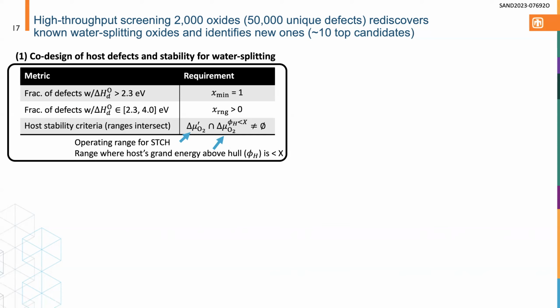And then we need at least one defect in the critical range. Nominally, you might want more than one defect in that range. And then the big thing that we also looked at was, what is the material stability? So going beyond just looking at energy above the hull, you have to also consider the host material stability as a function of oxygen chemical potential, because STCH is kind of relatively confined to this narrow oxygen chemical potential range